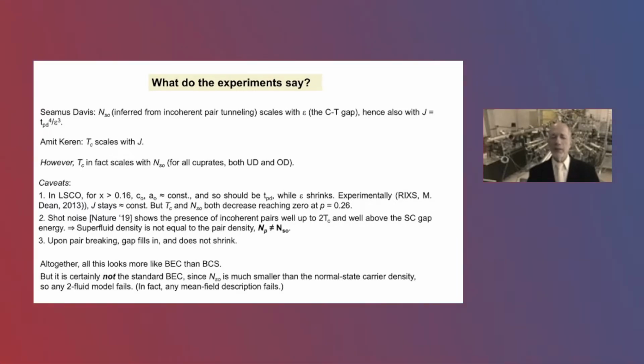But there are some more caveats. One is that in lanthanum strontium cuprate, when we go from optimum doping all the way to the overdoped side, there is very little change of the C-axis lattice constant and in-plane lattice constant and the copper to apical oxygen bond. So this hopping integral should not change actually. On the other hand, if anything, the charge transfer gap shrinks if it doesn't disappear.